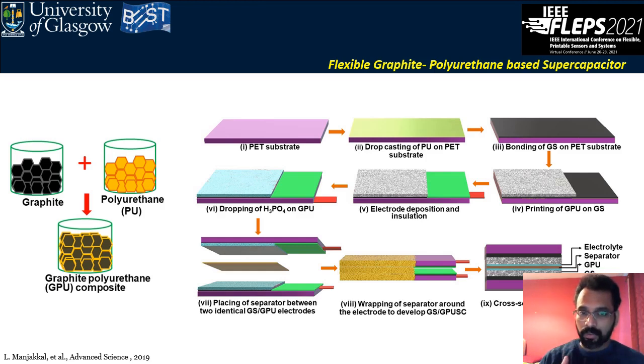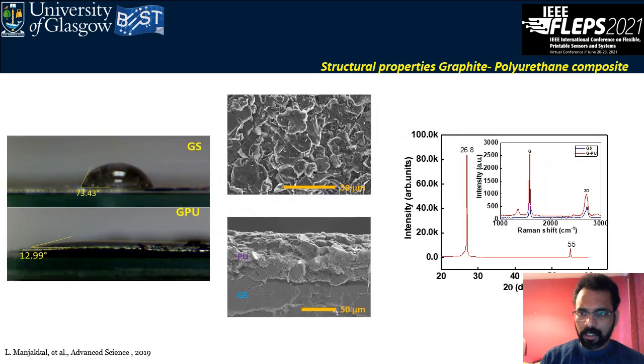Cellulose polyester is used as a separator for the supercapacitor fabrication. The advantage of cellulose polyester is that it holds the wettability for a long time due to the absorption capacity of the cellulose for the liquid. Here you can see the cross section of the electrode, and the major advantage of this graphite polyurethane composite is its surface, because to improve the electrochemical performance of the supercapacitor, the surface of the electrode needs to be in very good interaction with the electrolyte.